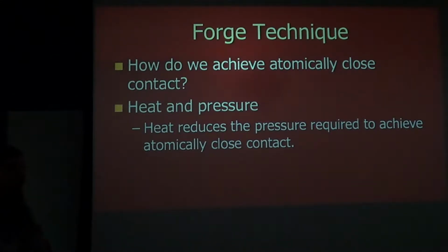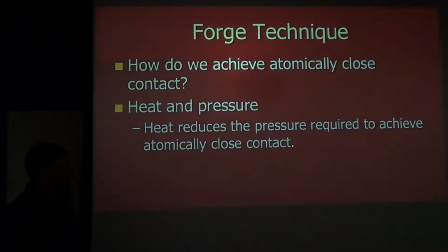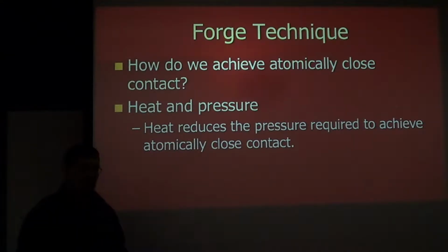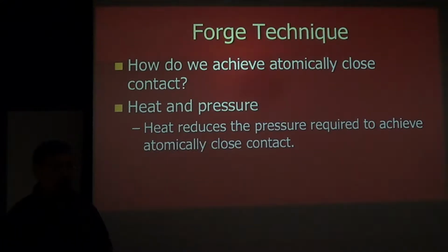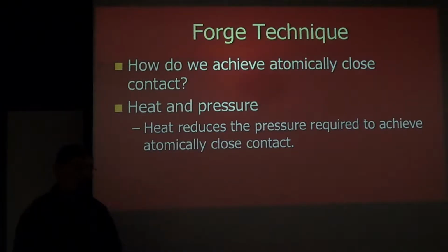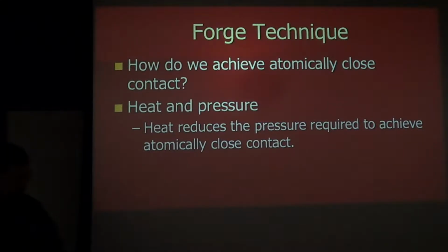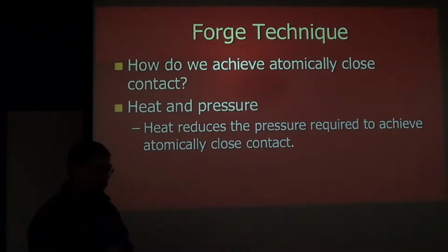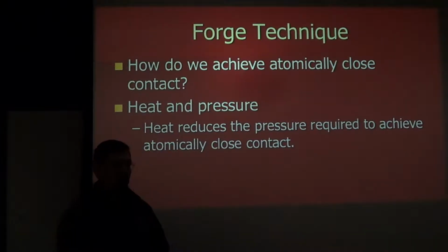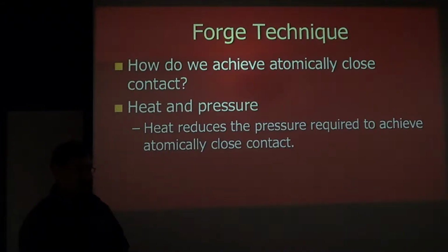Well, we are going to do it through heat and pressure. You don't necessarily have to use those things. I can come up with examples where you could do it without heat, right? If I had surfaces of materials which are naturally non-oxidizing, so let's say I had gold, which is a noble metal, it doesn't oxidize. So if I took two pieces of gold and I pounded them together at room temperature, they would forge weld. They would be bonded because the surfaces are clean, and it's a ductile, soft material, so it doesn't take a lot of deformation to get atomically close surfaces, and all of a sudden you've got a solid piece. So that's done in certain crafts.